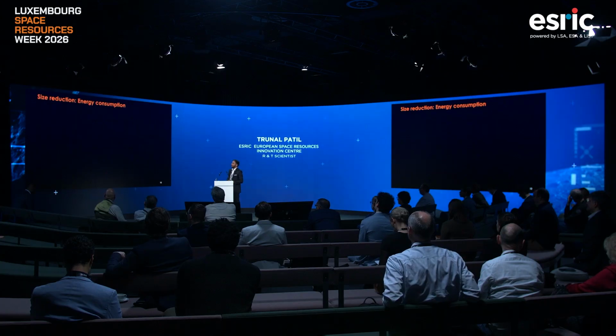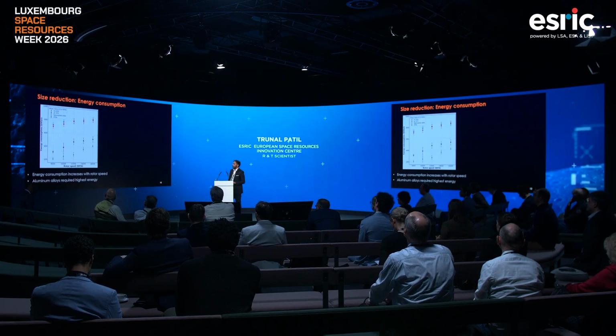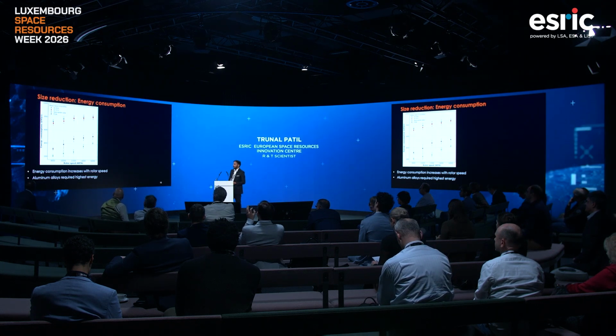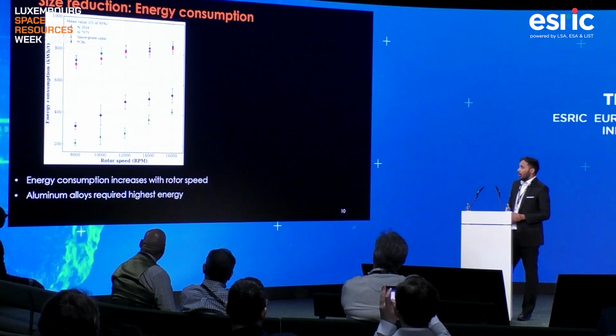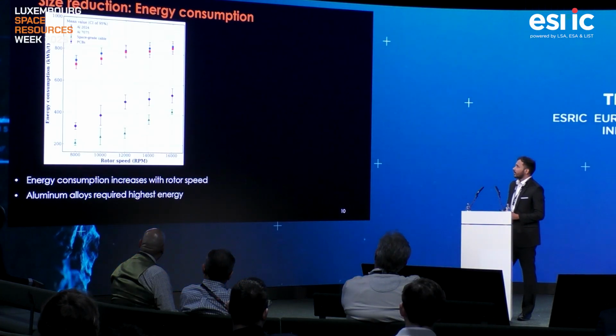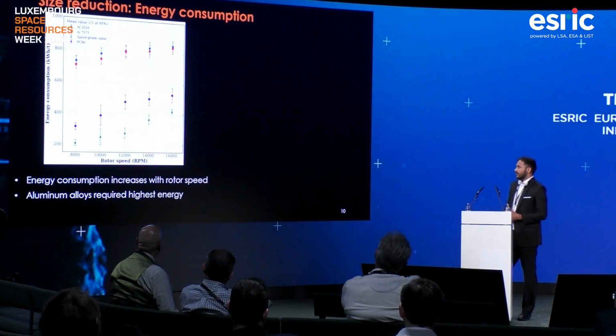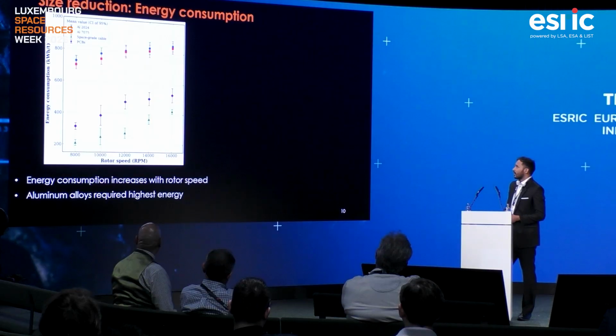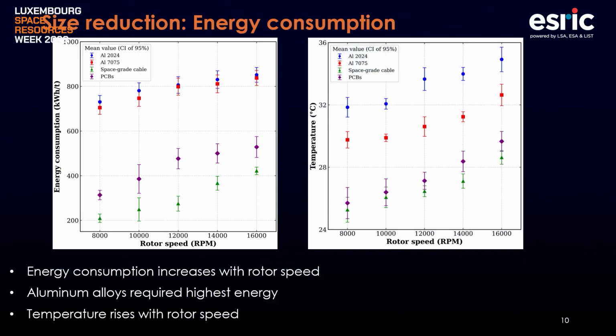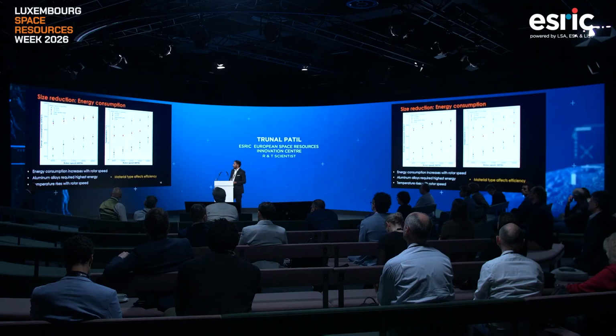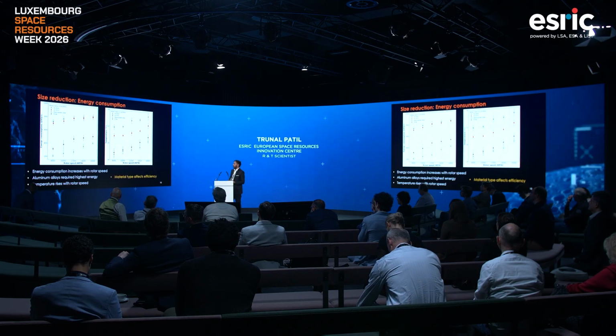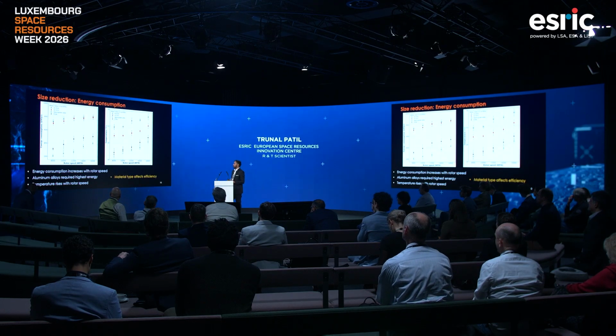Next, we also verified the energy consumption. We tested all three different feedstocks, aluminum alloys, space-grade cables, and PCBs, at different RPM speeds. What we found is that when we increase the RPM, the energy consumption rises, and aluminum alloys required the highest energy. We also measured the temperature inside the chamber, because we wanted to see how the temperature varies in this size reduction process. When we increase the rotor speed, the temperature rises, and notably there is a higher temperature rise for metal materials like the aluminum alloys. So this says the process performance depends on the material types, on what materials we are going to shred.